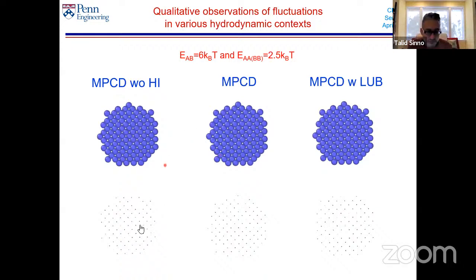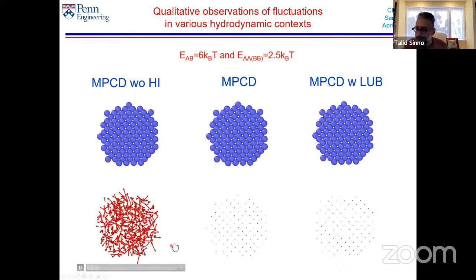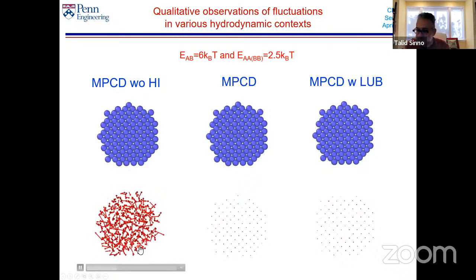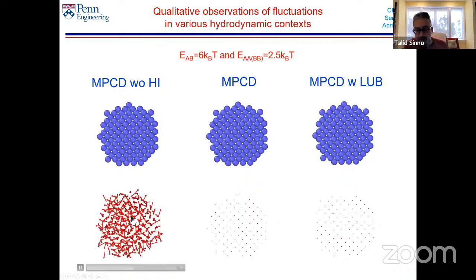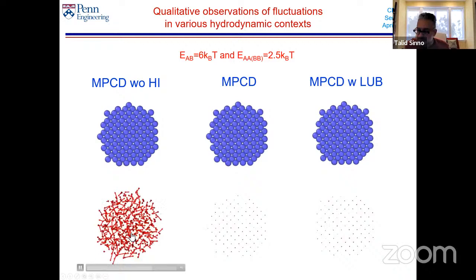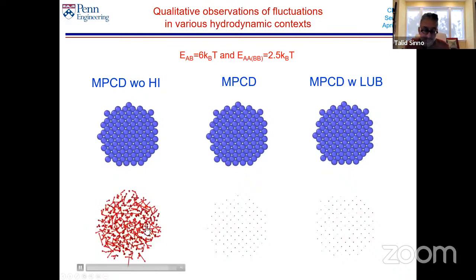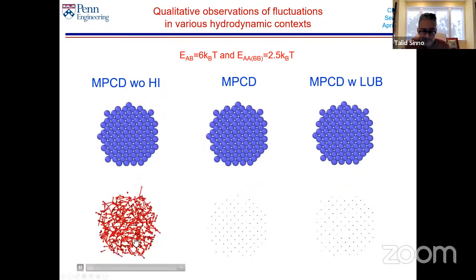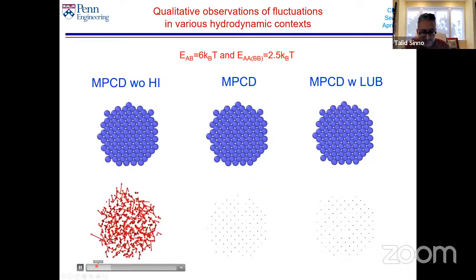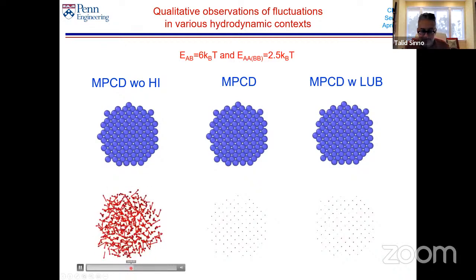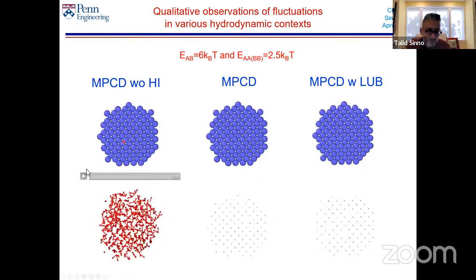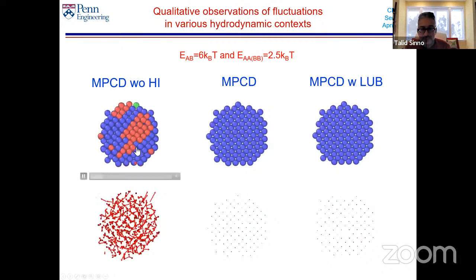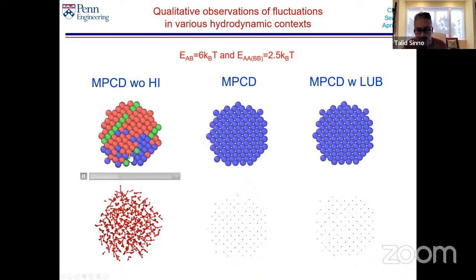So let me show you just a couple of quick movies. This movie here is a set of the instantaneous velocity vectors for each of the particles in a crystallite. And this crystallite is undergoing a transformation from cesium chloride, from BCC to FCC. And you can barely see anything in here. You can kind of tell that at the beginning, the lines are a little bit longer than later. That's the only signature that you have of the transformation. And this movie is the same exact data, but now we're colorizing everything so that you can see that indeed I go from cesium chloride, which is blue, to red and green, which is HCP and FCC. So this is without hydrodynamics.